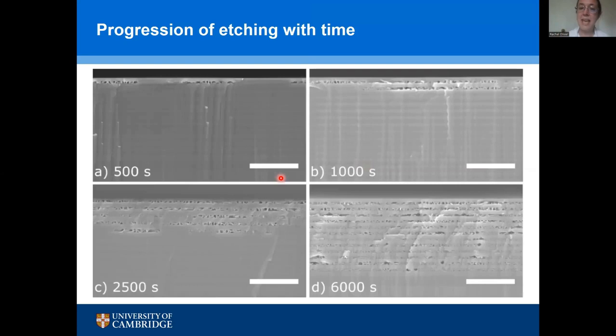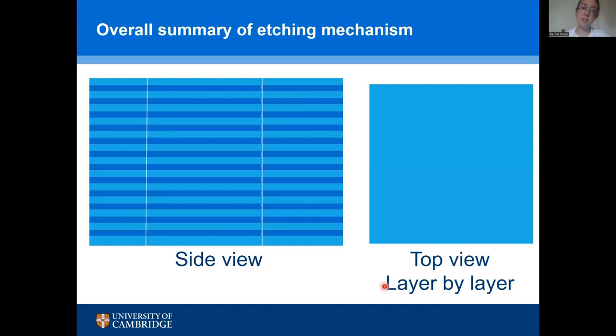So if we now look at how the etching of the porous GaN progresses with time, I've got here one of these doped, undoped multilayers. And if we look at it very early on in the etching, this is like we've stopped the etching and then cleaved the sample to have a look at what's going on. We can see we've just started etching the top layer. If we double how long we etch for, we finish etching the top layer and start on the second layer. If we extend the time further, we can etch through 4 or 5 layers. And then only at long times do we really get down to the bottom layers in this stack that we are etching.